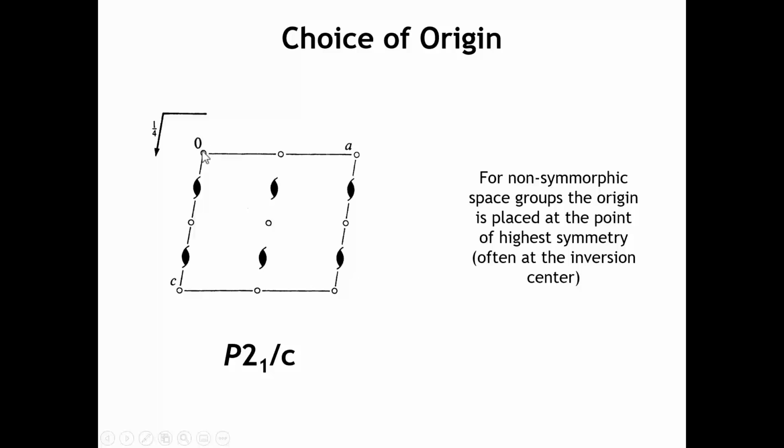You will find a variety of space groups for which there are two different choices of origin. And you'll see that when you're looking through the international tables. You just want to be a little bit cautious that if you are using the coordinates that go with, for example, setting 1, where we put the inversion center maybe where different rotation axes intersect, but really those coordinates go with origin choice 2, which might be, let's say, at the inversion center, that can confuse you. So just be aware that many space groups, or at least some of the space groups, have multiple choices of origin that are equally valid, and you'll find both of them in the international tables.